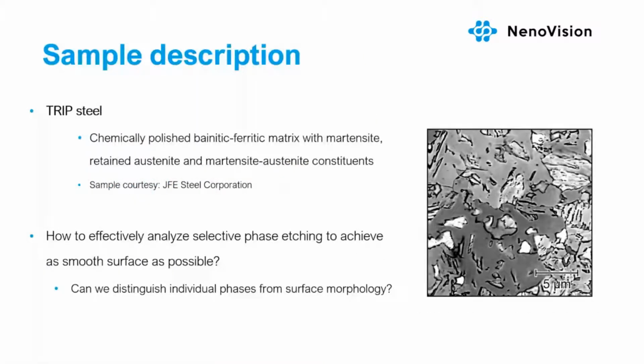We are going to measure two kinds of steel alloy. The first sample is TRIP steel, which is chemically polished. The aim of etching here is to fabricate a very fine and smooth surface. AFM alone gives us information about the morphology and about the roughness of the surface, but we are not able to determine the reason for the diverse etching rate or the selective etching. Because the steel alloy is composed of several phases visible in SEM, the correlation of AFM and SEM could provide us complex information about the sample surface.